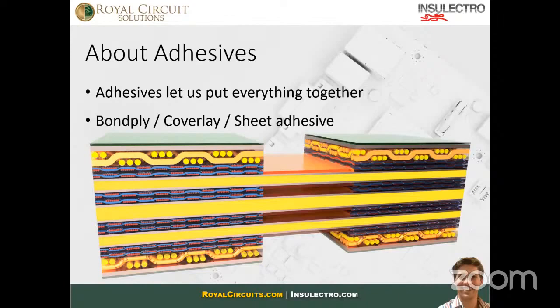If we have a loose leaf construction, which is what you see here, we wouldn't traditionally use a bond ply. But if we needed to glue two of these layers together to make some kind of microstrip transition vehicle, we would use a bond ply that'll glue the flexible cores together in the middle to make sure that our distances to ground from our signal are maintained throughout the bend and ensure we have consistent performance across our transmission.